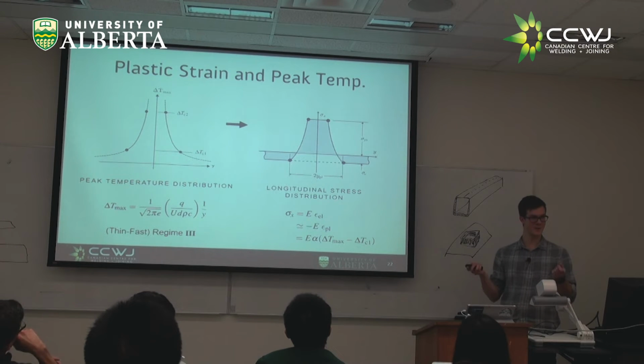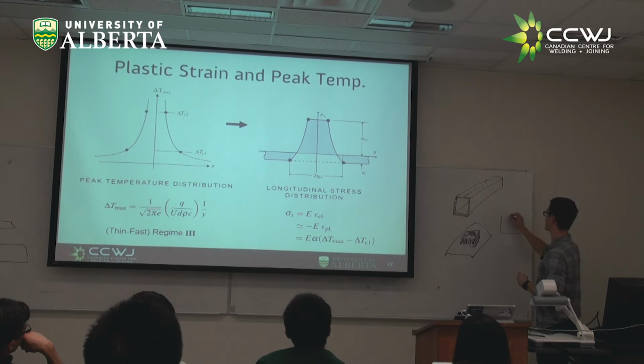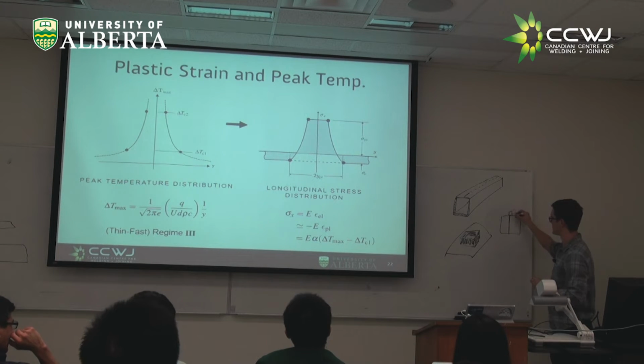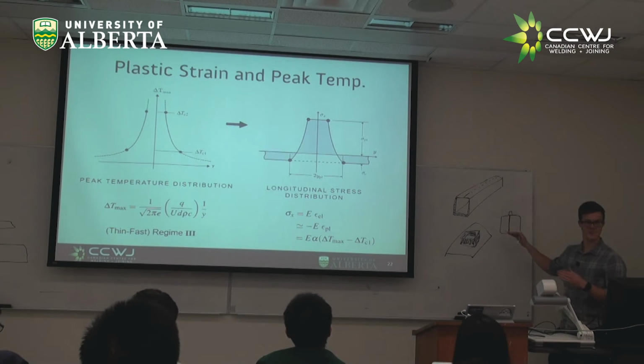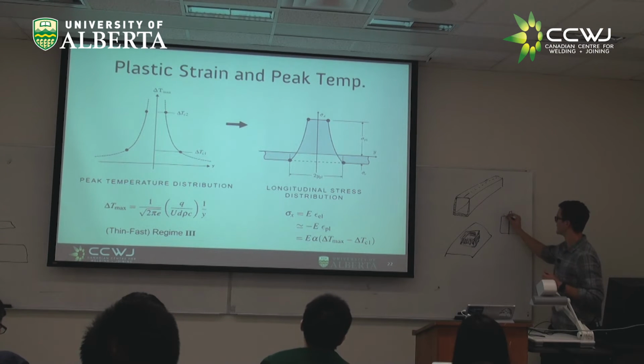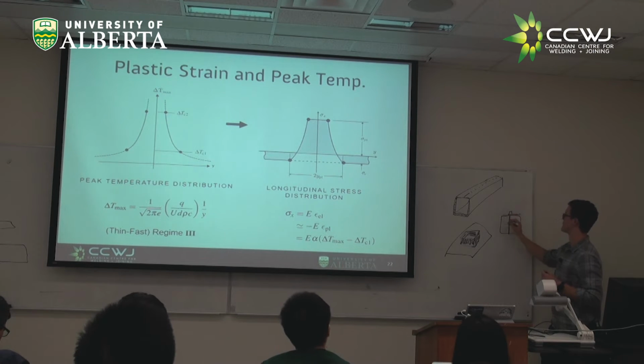So it's going to have some amount of distortion to develop some compressive stresses. What that means is if we have a plate here, and we have a weld down the middle, and we have some amount of tensile stresses here, the plate's not just going to sit like that. As these stresses develop, we're going to have to develop some amount of shrinkage all across the whole plate, which is going to shift the 0 point up a little bit to make our stress distribution look like that, because it has to be in equilibrium.